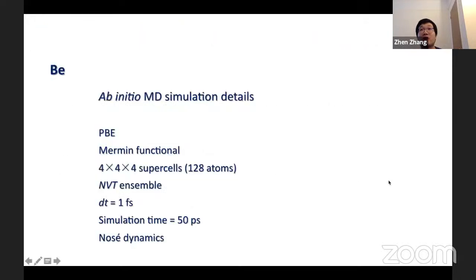Here are the ab initio MD simulation details. PBE was chosen for the exchange correlation functional. For metallic beryllium, the finite temperature Mermin functional was used. 4x4x4 supercells equivalent to 128 atoms were simulated in the NVT ensemble. Each MD ran for 50 picoseconds with a time step of 1 femtosecond. Temperatures were controlled by Nosé dynamics.